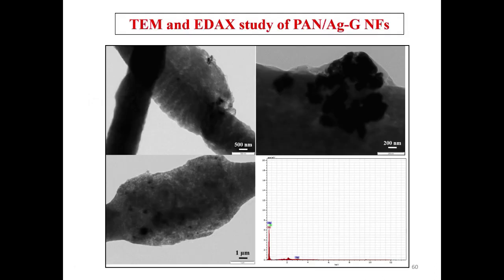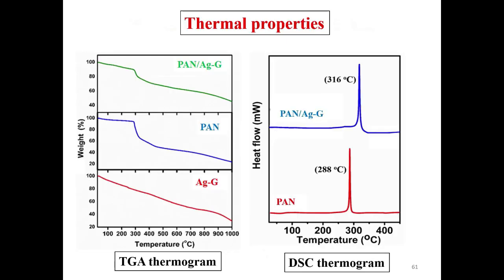This is the transmission electron microscopy, very highly porous. If you look into this particular patch, there is a decoration of silver graphene sheet over the surface of the PAN nanofiber. These are the PAN, these are the AgG nanoparticles over the surface, and a very highly porous material, meaning they are completely decorated or embedded inside the structure. Thermal properties: thermally highly stable as compared to PAN and AgG nanosheets.